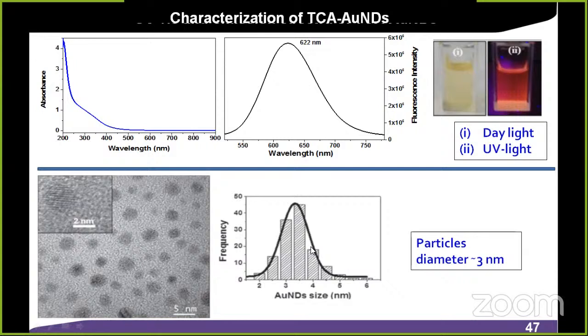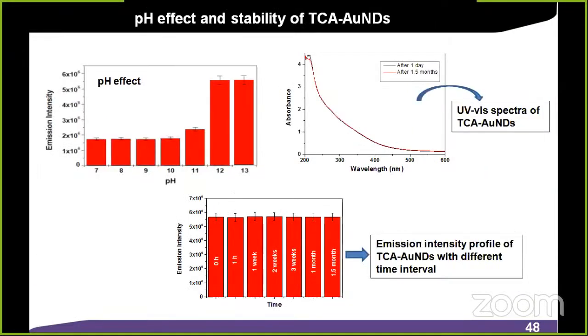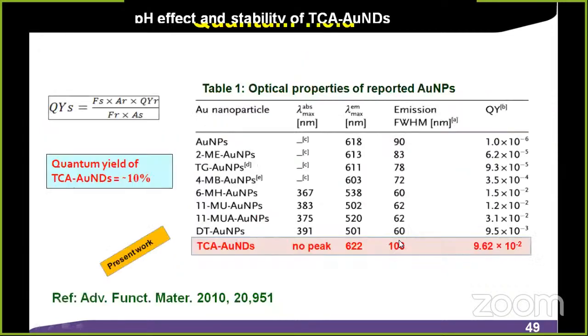This image, everything was done by myself only. Even the transmission electron microscope, when I was in Portugal, I imaged it by myself. Very interesting. And it's stable for 1.5 months. And for the pH effect, it is stable and high intensity is obtained at 12 and 13. And it is highly stable up to 1.5 months.